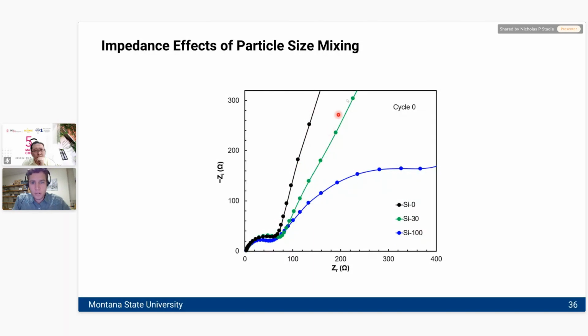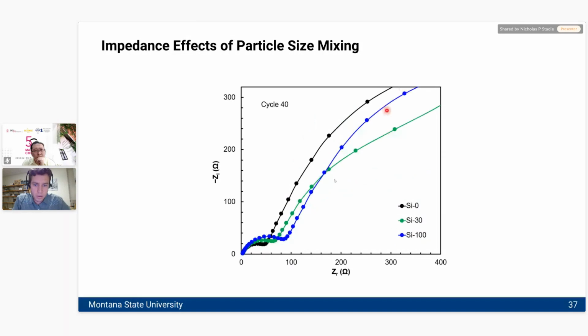The Si30 shoots just in between. So here we have a case where this really is now maybe something just in between these two phases, right, in cycle 0. Now, interestingly, as you continue to cycle those electrodes, the nano phase, which used to be the kind of least resistive one, turns out to be a lot more like the Si0. It's starting to act a lot more resistive, sort of similar to micron-sized particles, even though it's made purely out of very small nano-sized particles of silicon.